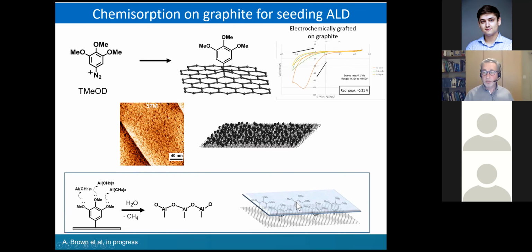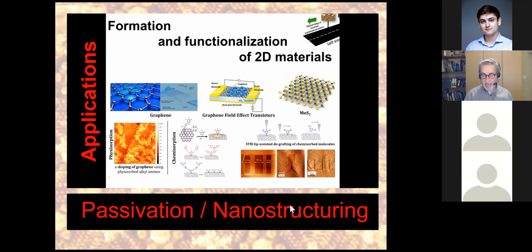Now you could argue, well, that's nice, but you do not have aluminum oxide directly on graphite or on graphene. You have it on top of a bridge layer. Well, the good news is that we can remove this bridge layer just by heating. At least we can break the bond between the covalently linked molecules and the graphite or graphene substrate.